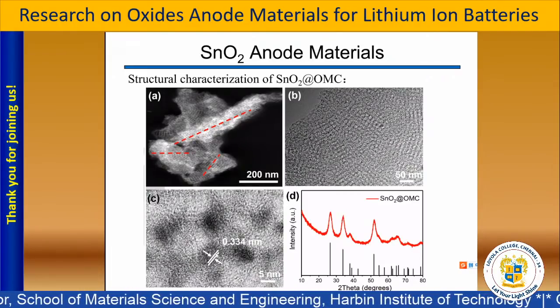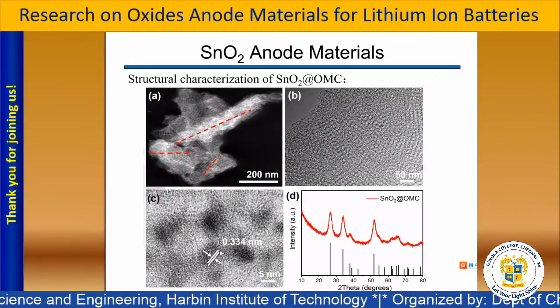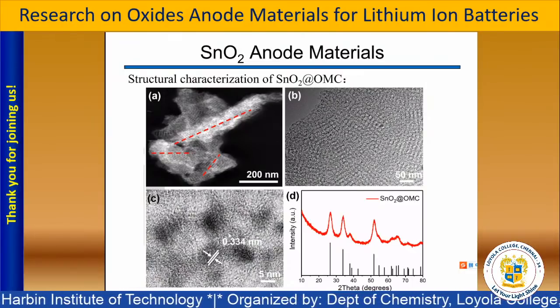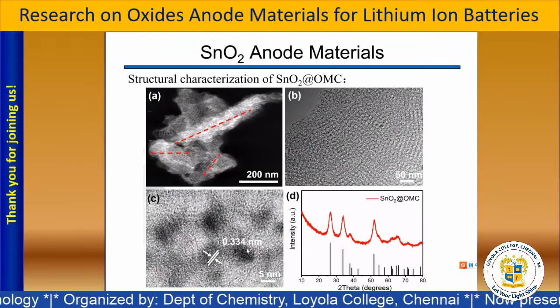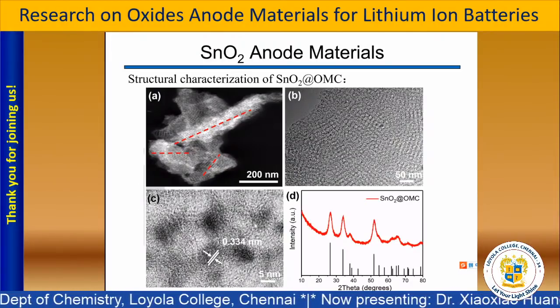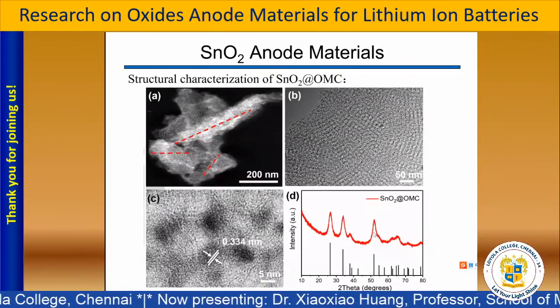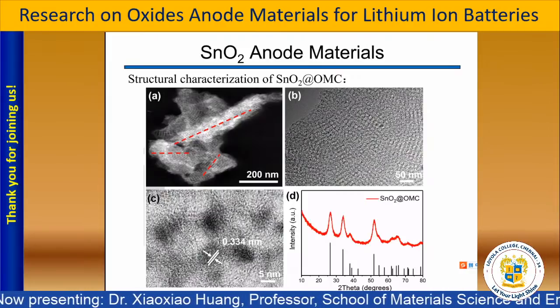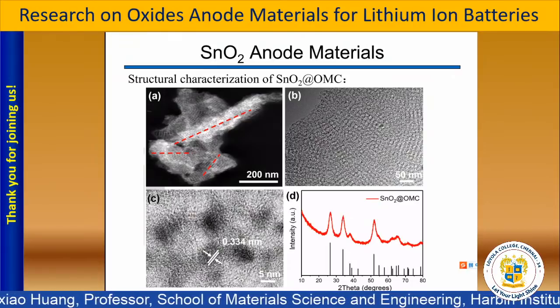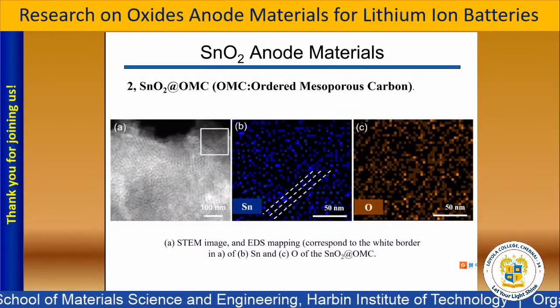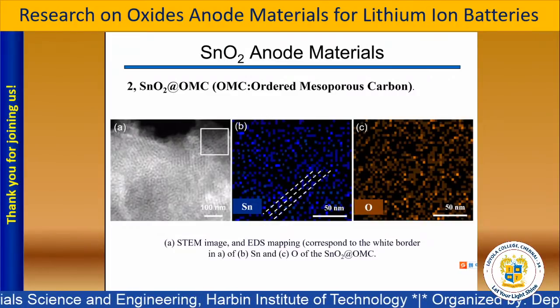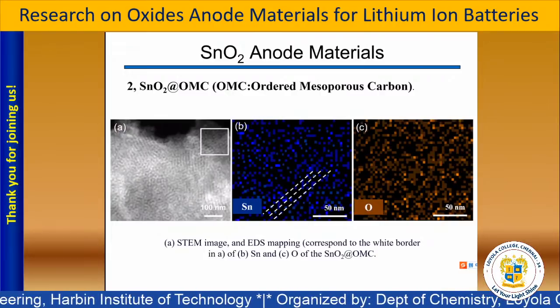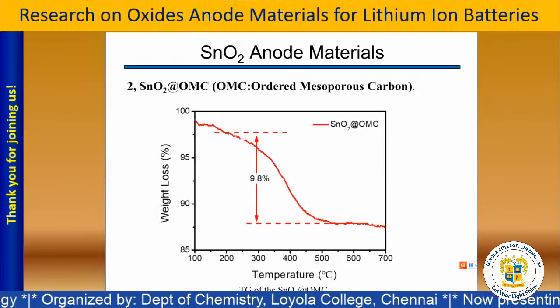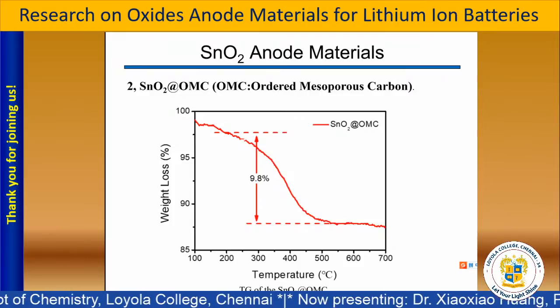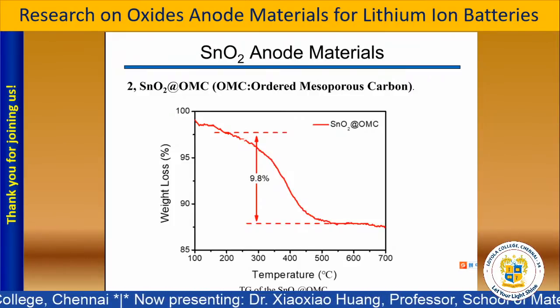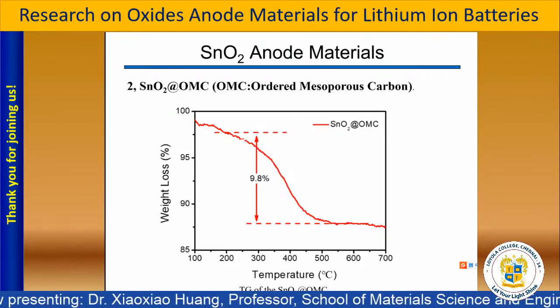And when we test the lattice spacing, we can get a very small size tin oxide. The size of the tin oxide should be about 5 nanometers. It's very, very small. And we get this value because we calculate based on the XRD result. This is the tin and oxygen mapping, and we can get the detailed microstructure of this material. The TG result tells us that for the tin oxide at OMC material, we can get a very high content of the tin oxide in this material.